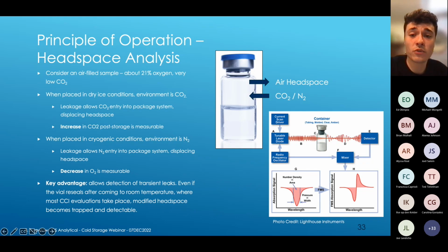Any leakage that's present in that vial is going to allow exchange of that headspace with the CO2 environment. And so we will lose air headspace and have that replaced with CO2 as the dry ice sublimates and that gas leaks into the package during storage. We can measure this increase in CO2 after storage on dry ice as an indicator of whether or not that sample leaked at these conditions.